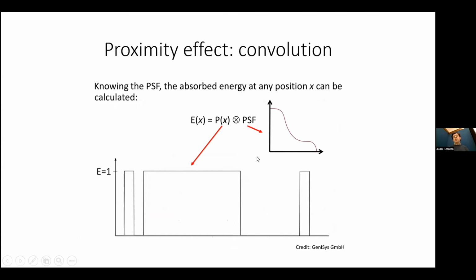So let's try with a one-dimensional example. You have this pattern, which is P of X, and then convolve it with the point spread function. There are two components to the point spread function in this example. You have the forward scattering, which is this slightly sharper, higher energy. And then you have the backscatter, which is much more distributed and at a lower level. But if you integrate it, this can actually be a rather large part of your exposure.